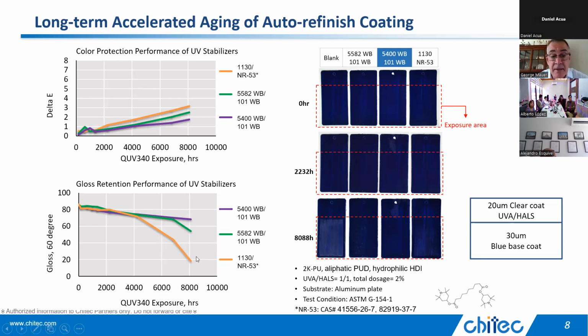Now, this test didn't have a rain part of the test, so it's a little bit easier test. And we'll see later on that you don't have to go to 8,000 hours in order to see a really big difference if you incorporate some exterior type exposure problems. And that would be something like rain, or actually in the automotive industry. For those of you that happen to work in that, you'll know that there's all kinds of different materials and things that come into play. Gasoline can hit your coating, or windshield washer fluid. We found car wash soaps can even take some of the UV absorber out of the film if it's not tied down well. So this testing is actually mild compared to what goes on in the field.